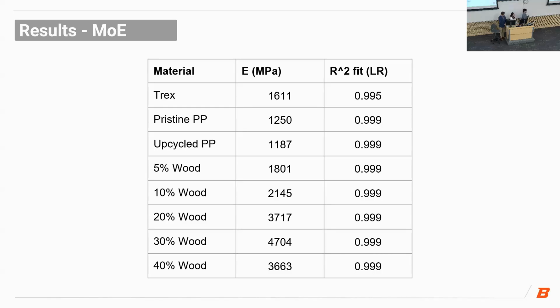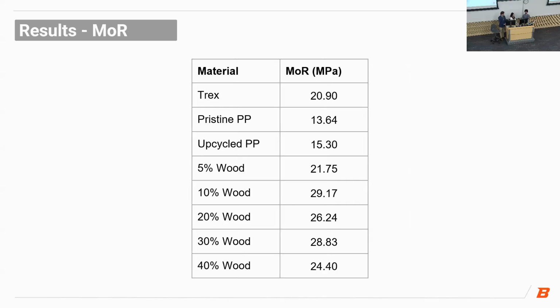And once we introduce the reinforcement material, we see a sharp increase in the modulus of elasticity. So we go to 1800 at 5%, 2200-ish at 10%, and 3800, a massive jump from the 10% to 20%. And at 30%, we peak at around 4700 megapascals. And then once we hit 40%, we then dip back down. So 30% was peak for us.